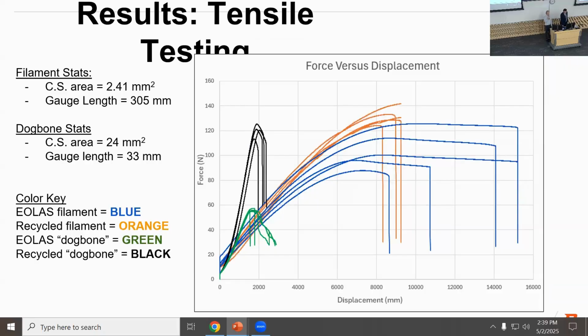And here are the results from our tensile testing. We put all of our data onto one chart. As seen in blue and orange, those are the filament samples for both recycled and purchased. And then in black and green are the dog bone samples. You can see there's a big difference in displacement, and that's completely due to the gauge length difference between the samples. The dog bones were 10 times shorter at 33 millimeters than the filaments. We also measured the cross-sectional area. Since this is a force versus displacement chart, we also want to figure out stress.